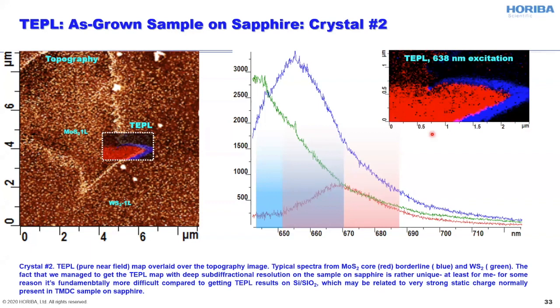But anyway, in this crystal, we managed to directly image the distribution of this transition area along the junction between the molybdenum disulfide core and tungsten disulfide shell on the sample grown on sapphire. And the width of this transition area was found to be about 150 to 200 nanometers, which is quite consistent with what we observed in tip-enhanced Raman scattering maps of similar crystals.